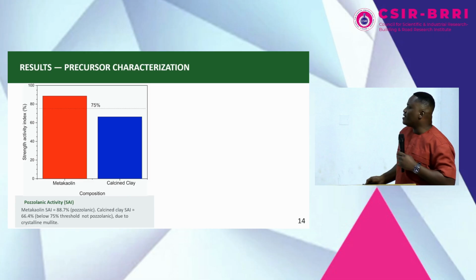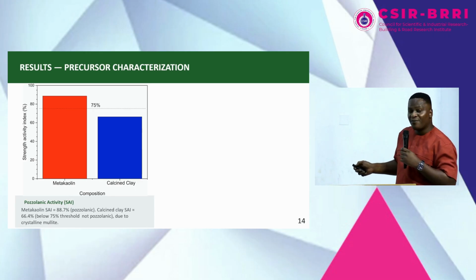I realize that the strength activity index for the metakaolin is 88.7%, whereas that of the calcined clay is around 66.4%. And according to this strength activity index, it means that the calcined clay, at the strength level, is not performing very well. It's trailing the mark, which is 75%.